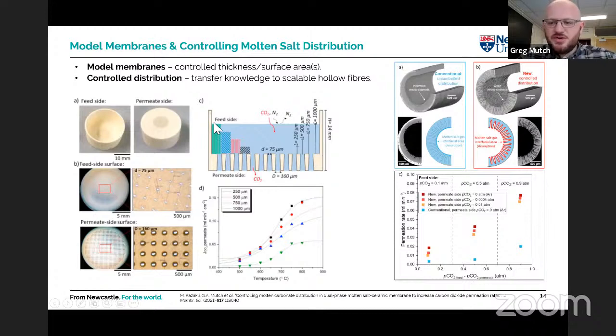And what we have is a structure or a membrane that has very high surface area on the permeate side, very low surface area on the feed side, and we can vary the thickness without changing the surface area of the membrane. And then we can swap the way we feed the gas as well and change the surface area for the feed and permeate side. So we can get lots of useful information about the transport mechanism using structures like this. And in this particular case, we found out that the permeate side surface area of the membrane is the rate limiting step for transport across the membrane. So CO2 comes in, it diffuses through, and it leaves the membrane. The surface area on this side of the membrane is the rate limiting step.